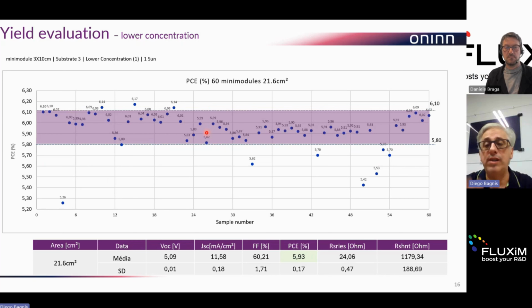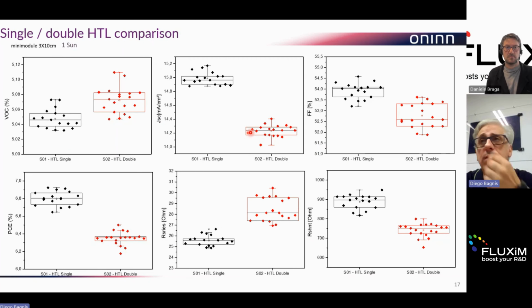So just to mention how important it is, not only the material that you are using, not only the process, but also, in this specific case connected to the yield, the concentration of the formulation and the solubilization of the material inside. Another part that I mentioned in the beginning was exactly the HTL, and it's possible to see that when you use the single or the double HTL, the performance is slightly different. With the double HTL you maybe have a slightly better standard deviation, but with the single, for this specific formulation, it's possible to get better performance. This is not a general rule.